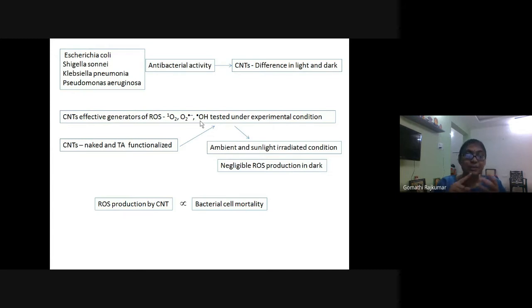But unfortunately, when we took flavonoids such as catechin, apigenin, rutin, or quercetin, what we found was the functionalization was not very effective, and these compounds started to lose their property when the temperature was increased from the ambient condition. Whereas the phenolic acids such as tannic acid and gallic acid behaved differently because there was no loss, and we could obtain a very good functionalization.